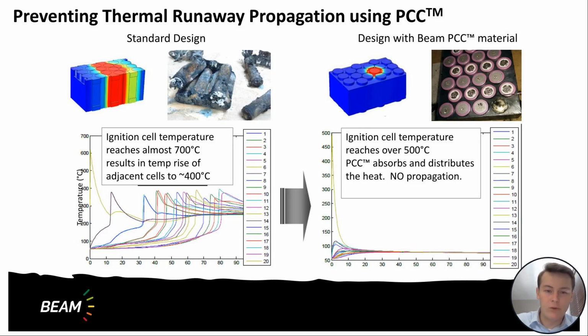You can see that on the left where we did not have PCC between the cells and they were just held in place by PVC, you have the initial spike in temperature from that failing cell on the far left at time 0. And then within 10 seconds, you have the first initial propagation of the neighboring cell. And it's just a domino effect beyond that throughout the entire pack. And so that gives a good overview of how the propagation occurs and how it looks from a data perspective. You can see the temperatures there exceeding 600 degrees in the initial, and then cascading failures in this particular pack were still close to 400 degrees Celsius.